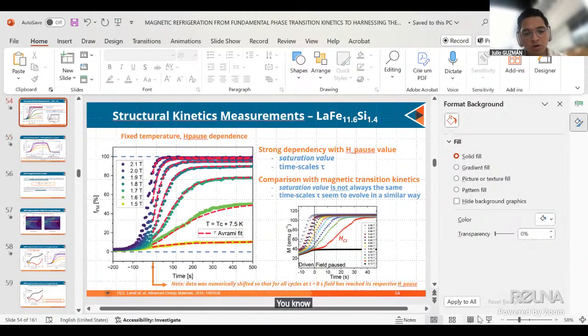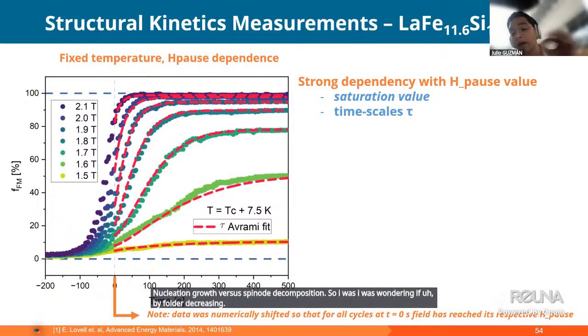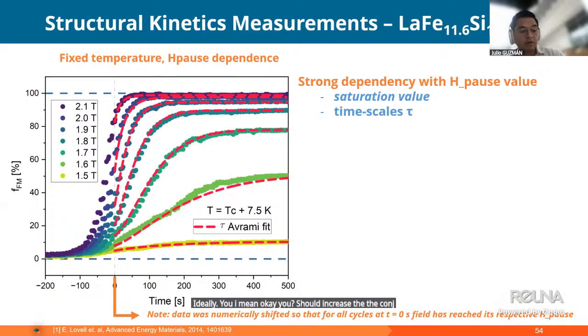When you were giving your talk, I was really thinking about nucleation growth versus spinodal decomposition. So I was wondering if by further decreasing, getting away from the critical point, you should increase the conjugated field in this case to arrive to the spinodal line. So I was wondering if you saw further increase of the dynamics, if you have done any in-depth study about how dynamics look like when you follow the spinodal line.